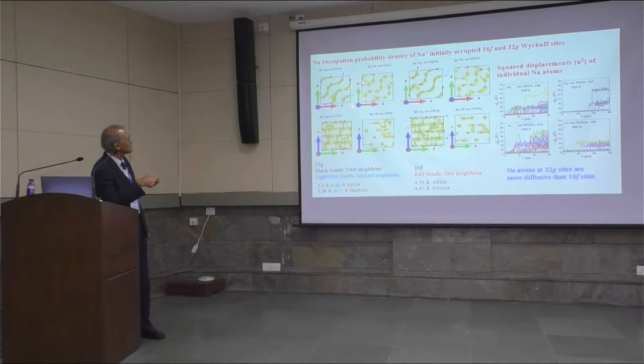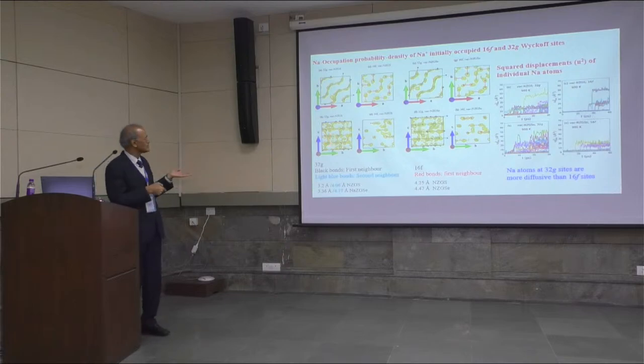atoms in a plane, and they also have atomic diffusion or jumps across. So this is the AB plane in the crystal structure, and if you plot the BC plane, C is along the perpendicular direction. So these chains, there are also jumps between the chains along the C direction.